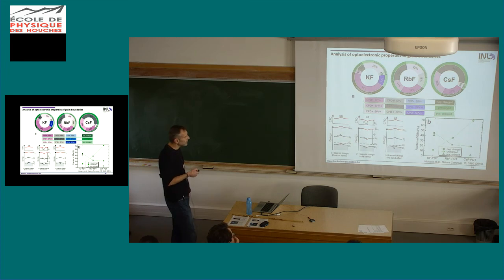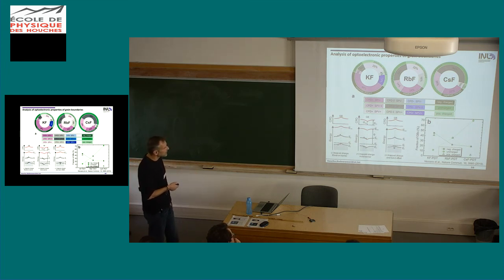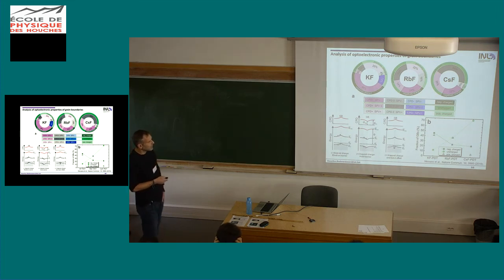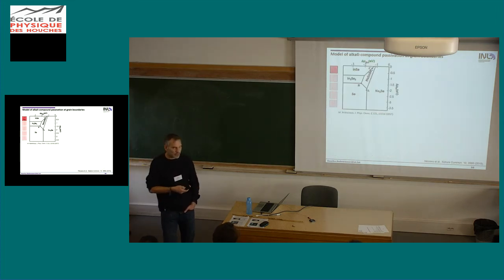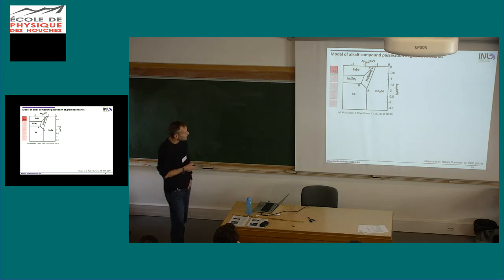So if we plot these fractions of grain boundaries as a function of charge, the negative charges are going down as we increase the weight of our alkali element. The uncharged increased, and also the positive charged ones go down. But the major point is here the uncharged increase. So how can we understand this? Uncharged means we see some modification due to a different material at the grain boundary, for example.